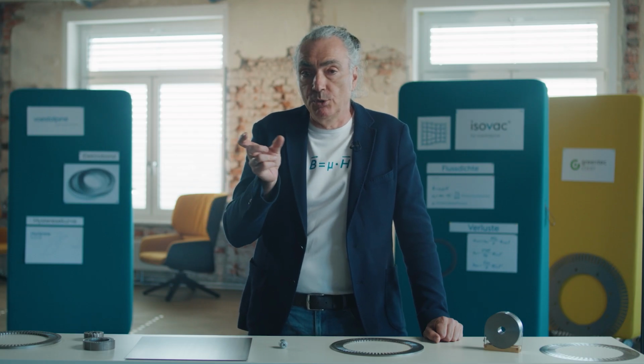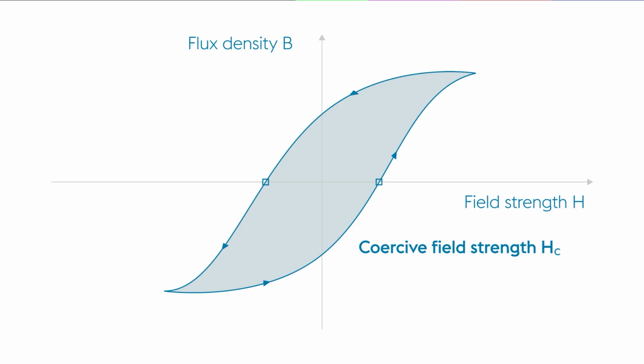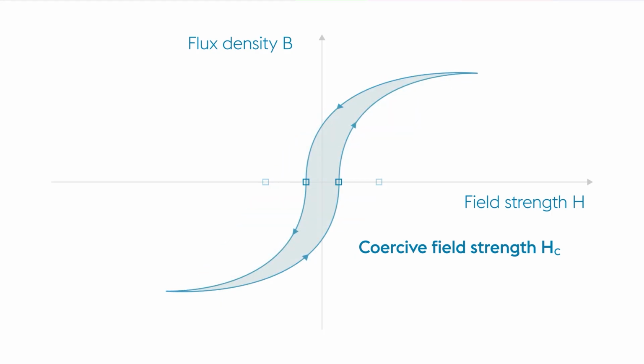This can be 50 times a second when the power comes from an electrical socket in the wall, but it can be a few hundred times higher than that, for example, in the traction motor of an electric car. And every time the polarity is reversed, energy is consumed to realign the dipoles and demagnetize the material again. The deciding value for this is the coercive field strength. The smaller it is, the narrower the hysteresis curve will be, and the smaller the area it covers. It also leads to lower hysteresis losses.